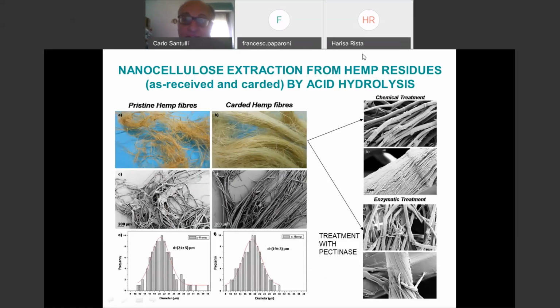You can extract nanocellulose also from hemp residues. From waste, it makes more sense, since the yield is low and you get little nanocellulose from your initial fibers. You can think of starting from pristine fibers or from carded fibers, which were production waste, not good for textiles. You can treat them with pectinase in order to remove the natural glue which is present on hemp, and you can treat them chemically as well with sodium hydroxide.